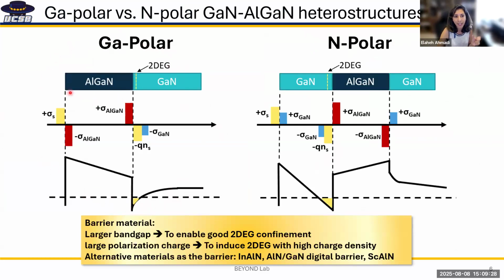If you look at a simple gallium polar GaN HEMT structure, the most simple one is you have the gallium nitride, GaN, and you cap it with 20-30 nanometers of aluminum gallium nitride, which is a larger bandgap material. Because of the polarization charges that I talked about earlier, we get a net positive polarization charge at this interface, where the two-dimensional electron gas forms. Now, instead of this AlGaN, the large bandgap material, you can look at other alternatives like indium aluminum nitride. People have looked at that, and most recently, scandium aluminum nitride is being explored as the barrier material.